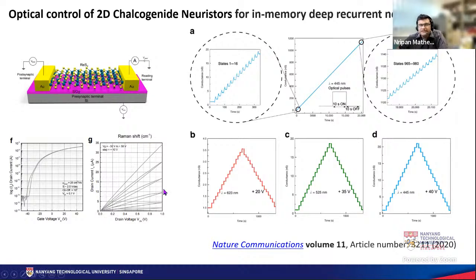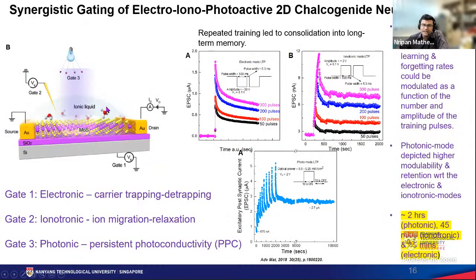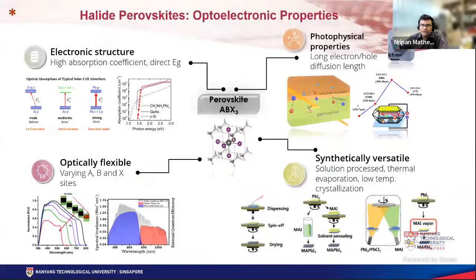But even when we were working on these three-electrode devices, and although we were pretty successful in making them work, what we always knew was that many of the dynamics that we see in these transistors don't really come from the semiconductor, but from the ionic dielectric sitting next to the semiconductor. So we definitely wanted to go towards a system which had ionic-electronic coupling. In my other work, I work very heavily on halide perovskites for solar cells. And we decided to focus on these material systems as well for neuromorphic applications, because these are ionic semiconductors as well.